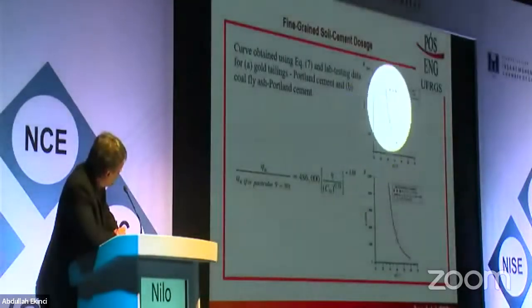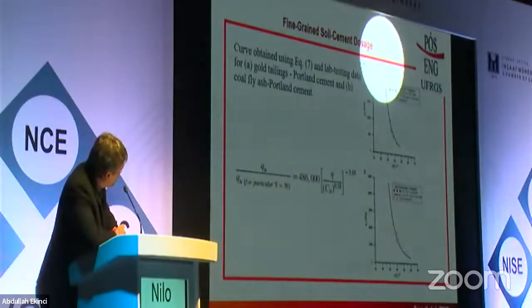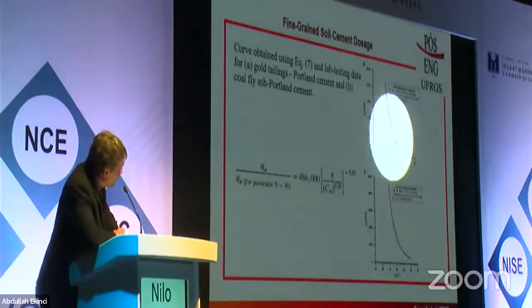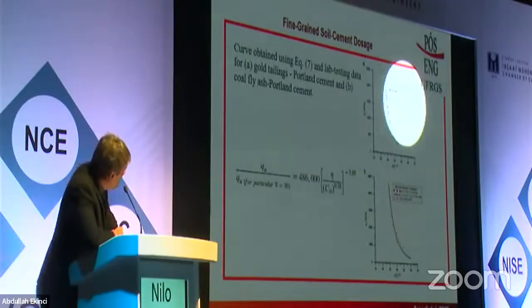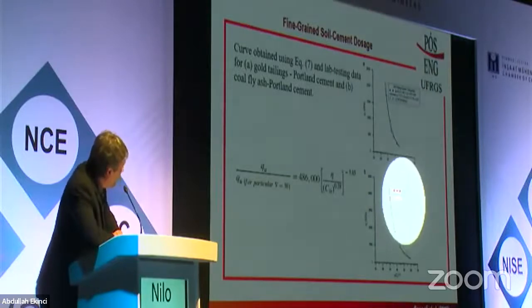These are just examples in which I have just one point, for example this blue one here at the top, and I could draw the curves, and all these other points are lab results that we carried out later. They were not used to fit this curve. We just have one point, and then the others really fit the curves. This is for another material, gold tailings, and this is for coal fly ash tailings, just to give an idea.